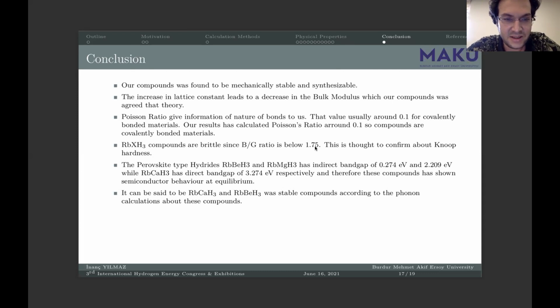The perovskite type hydrides, rubidium beryllium H3 and rubidium magnesium H3, have an indirect band gap of 0.274 electron volts and 2.209 electron volts, while rubidium calcium H3 has a direct band gap of 3.274 electron volts respectively, and therefore these compounds have shown semiconductor behavior at equilibrium.